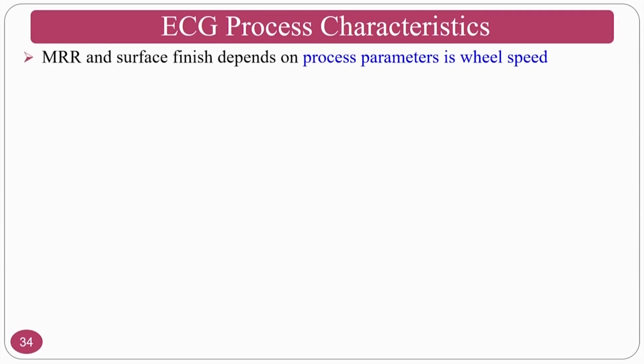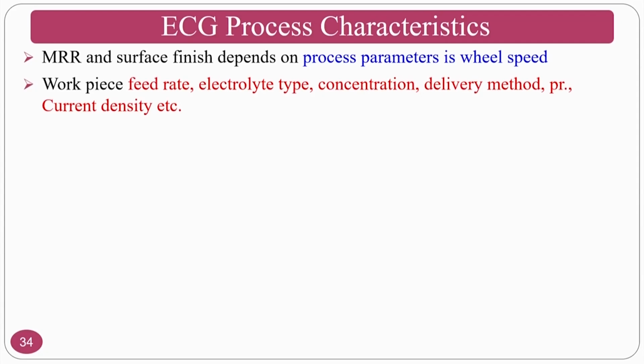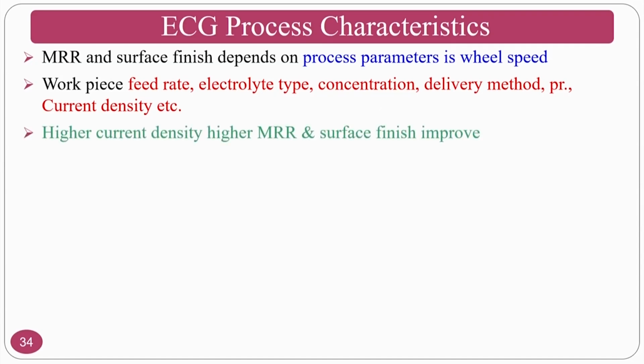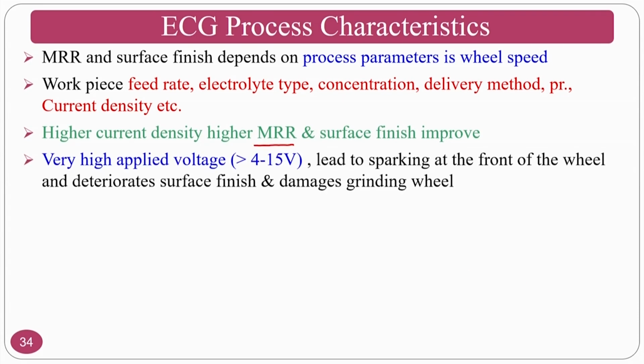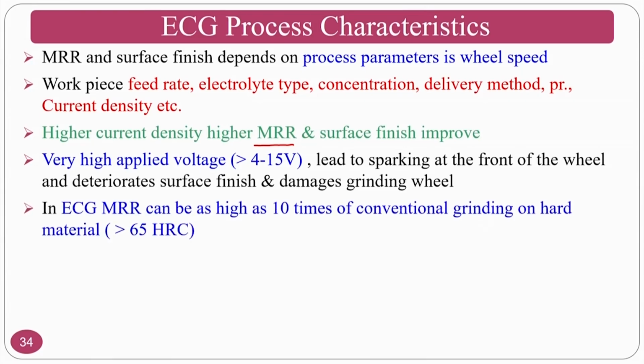So, electrochemical grinding process characteristics: MRR and surface finish depend on the process parameters, that is the wheel speed, workpiece feed rate, electrolyte type, concentration, delivery method and pressure. Current density also plays a major role in the electrochemical grinding process. High current density means you will get a high material removal rate and the surface finish also improves. Very high applied voltage leads to sparking at the front of the wheel and deteriorates the surface finish and causes damage. That means that you should not go for higher voltages.